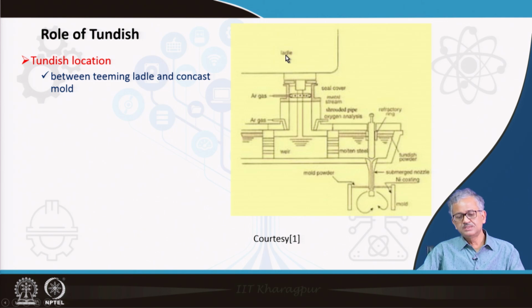If you see, this is the teeming ladle and this is the tundish, and whatever you can find here is the liquid steel stream. Surrounding this stream you can find a cover, and in that cover you purge argon gas such that the liquid steel is poured under an inert argon atmosphere. This is called argon shrouding of the liquid stream. Okay. So, you are shrouding with argon gas. The argon gas goes in from the top, and there is also some injection at the bottom, such that you can maintain a completely inert atmosphere through which the liquid stream comes out.